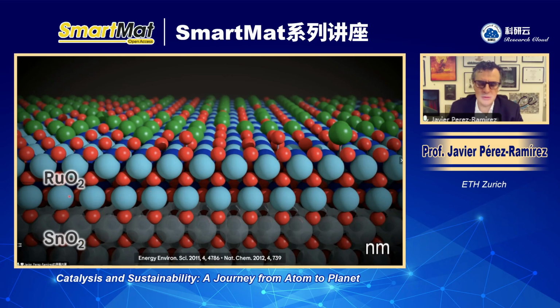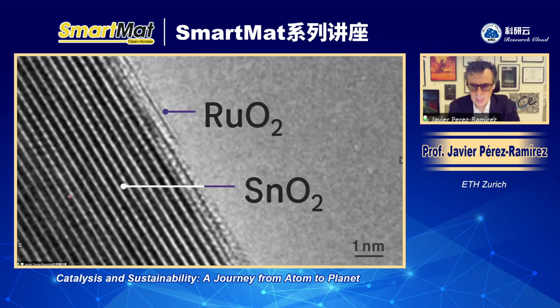on tin oxide. Both ruthenium oxide and tin oxide possess the rutile structure, rendering this film type architecture for the ruthenium oxide, which makes a very high dispersion of the active phase, and most important, a very high stability because of the lattice matching between the active phase and the support.